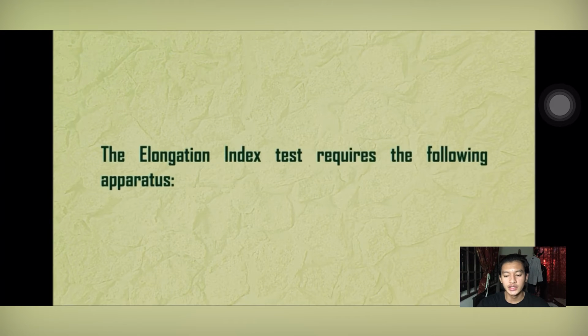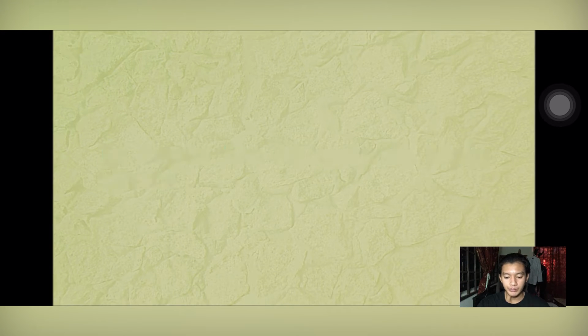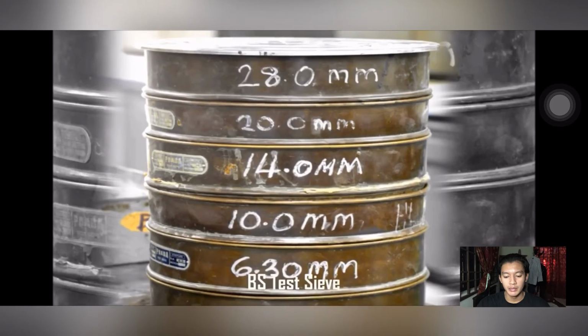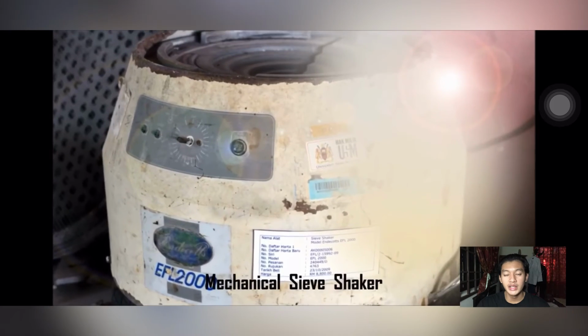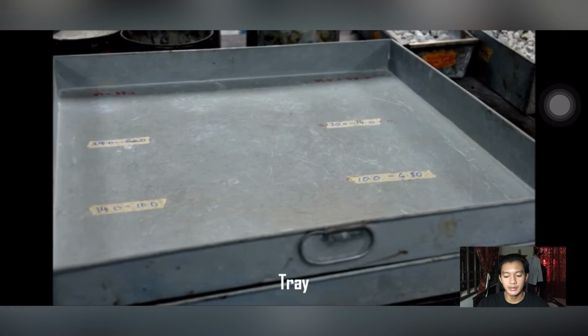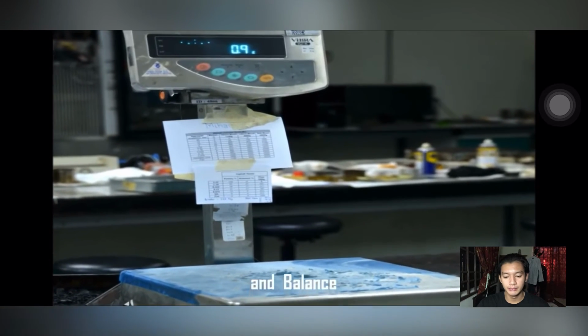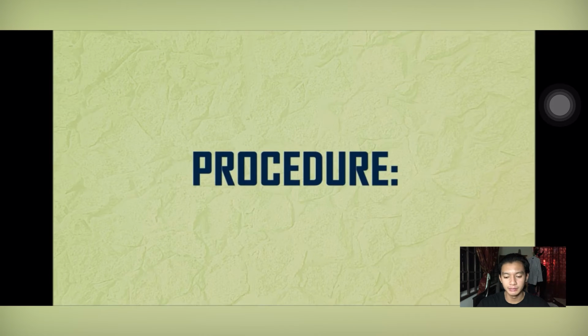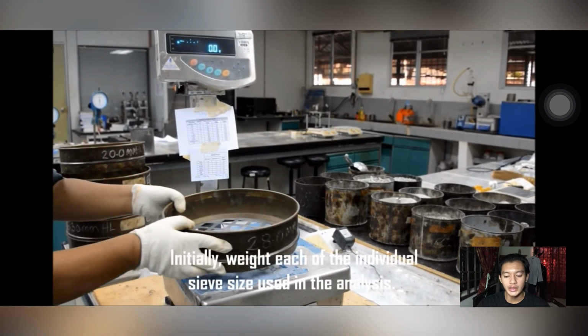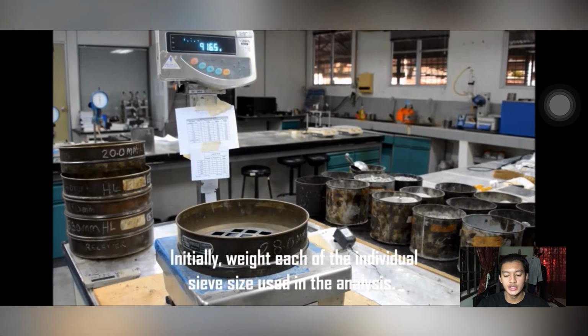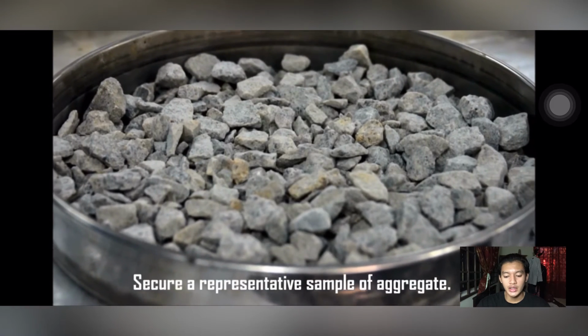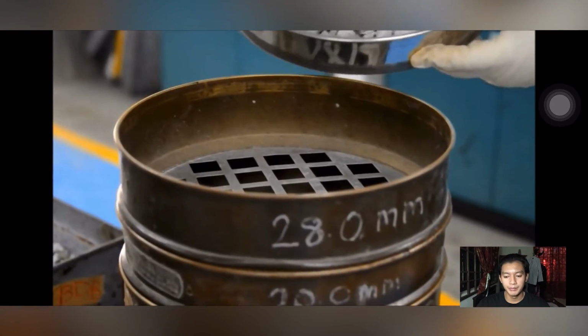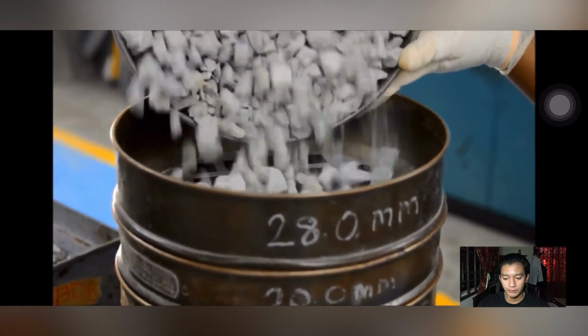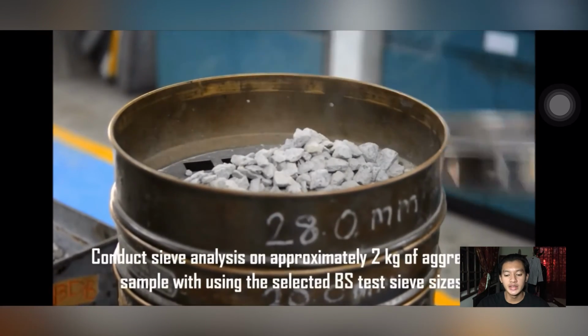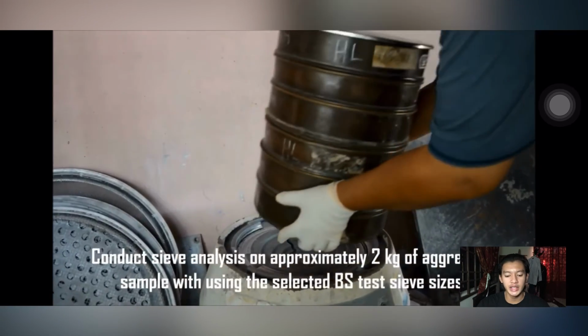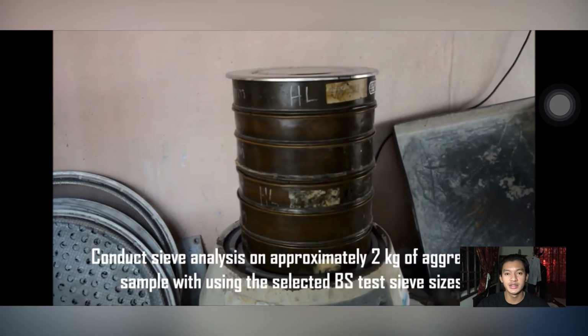The elongation index test requires the following apparatus: length gauge, BS test sieve, mechanical sieve shaker, tray, and balance. The procedure. Initially, weigh each of the individual sieve size used in the analysis. Secure a representative sample of aggregate. Conduct sieve analysis on approximately 2 kg of aggregate sample with using the selected BS test sieve size.